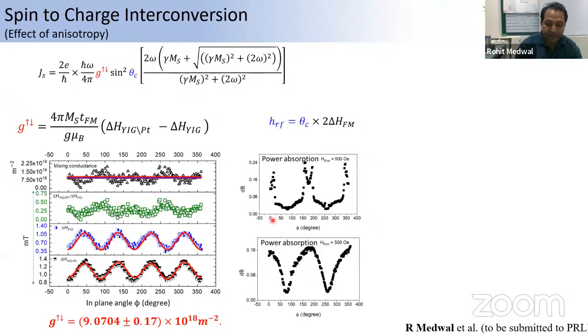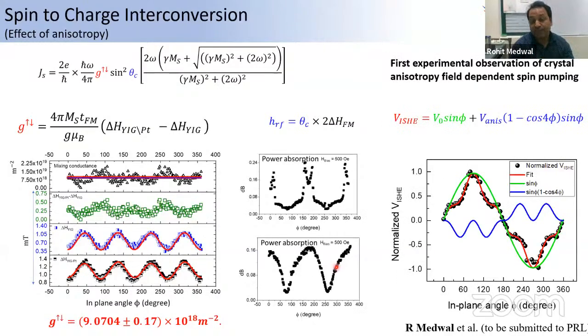Whereas when I measure the HR for the precession cone angle, I clearly see the 4-fold anisotropy along with a uniaxial anisotropy in the system. That is from the power absorption measurement, which is a separate measurement from the device measurements, and both measurements show exactly the same effect. When we deconvolute this, we clearly observe a sine theta curve because of the ISHE or device symmetries, and we are also adding one more contribution to the ISHE voltage, the anisotropic contribution coming from the crystal field anisotropy of the system. This is the first demonstration, so clearly shown, that the anisotropy of the ferromagnetic material also purely affects the inverse spin Hall effect voltage. This is the publication we are going to submit soon.